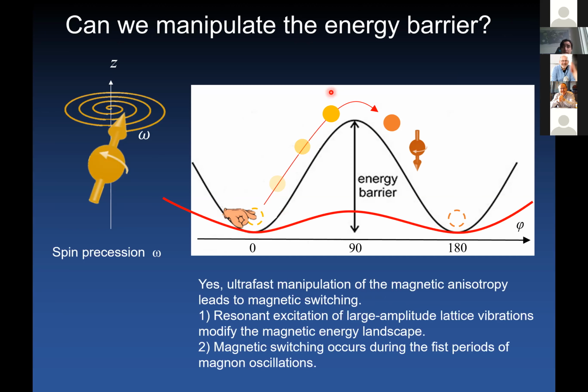In our experiment, we aimed not at overcoming the energy barrier, in a sense, but to manipulate the energy barrier itself. So the question that we asked ourselves is, can we manipulate the magnetic anisotropy on ultrafast time scales in order to lower the energy barrier, induce some coherent spin precessions, and an easy transition from one spin state to a competing one? And I want to show you that this is indeed the case, that if you excite resonant large amplitude lattice vibrations, you can modify the magnetic energy landscape sufficiently to allow for magnetic switching to occur.